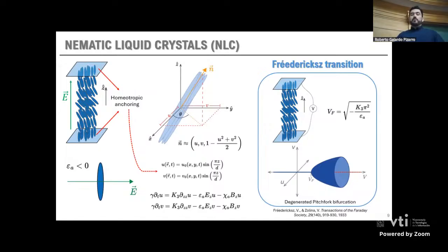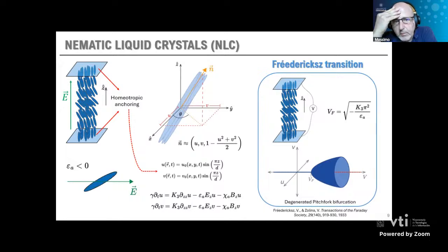And I don't have the plot here, but there is an experimental result: if we plot the intensity of the light that we see in the camera, there is a point for the voltage in which this intensity starts to decrease and then starts to increase again. And it happens several times. So I suspect that every time this happens is a point in which we are achieving other modes in the vertical direction. So for the voltage that you have, you are with M equal to 1.